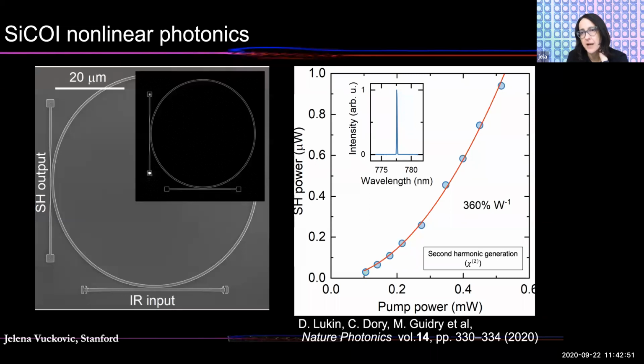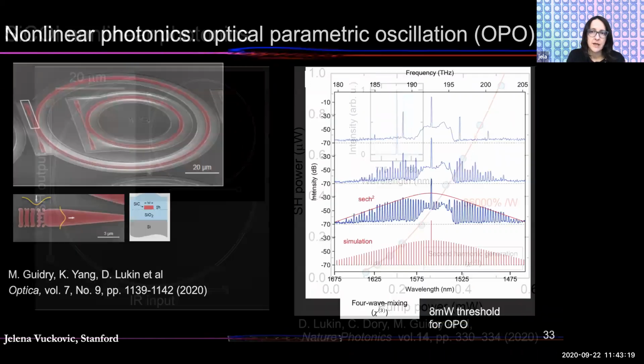In silicon carbide, we measured efficiency, and this is efficiency measured on the signals coupled to waveguide of 360% per watt. But at that time, we had Q factors for resonators that are smaller by a factor of around 10 or more, a Q factor of 100,000 relative to millions that we have now. So we think that this number actually should be now much higher, probably by about 2 orders of magnitude. And we're working on repeating the measurements.